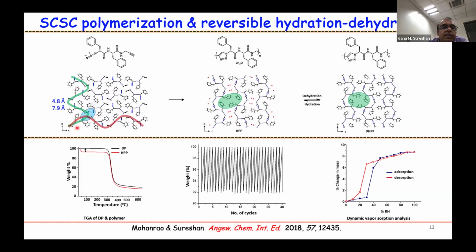So upon heating at 60 degrees centigrade, this reacts completely along the vertical direction. And this is the polymer structure. Now you see two dots. These two dots are water molecules. This takes water molecules from the atmosphere during this reaction to fill the space. And you can see these water molecules easily dehydrate because they are very loosely bound to the triazolyl nitrogen, with very weak hydrogen bonding. You can get the waterless form and do the hydration and dehydration n number of times. It dehydrates at room temperature to 50 degrees centigrade. If you blow dry air, it can dehydrate this hydrated form.